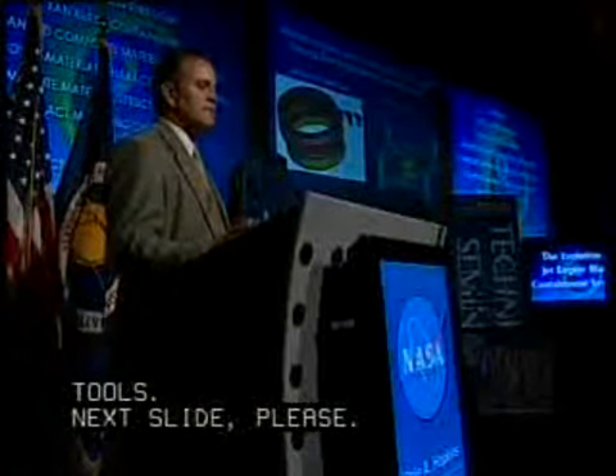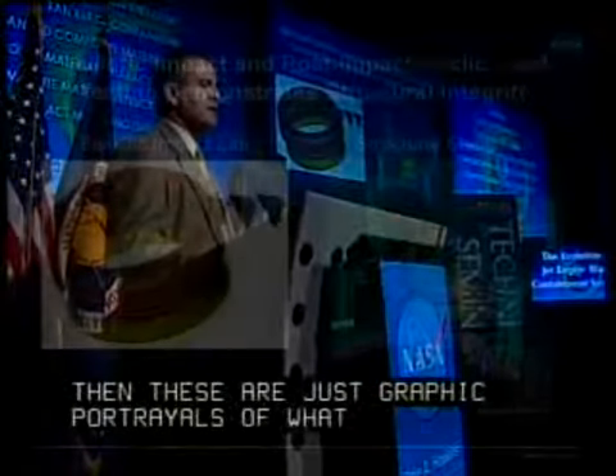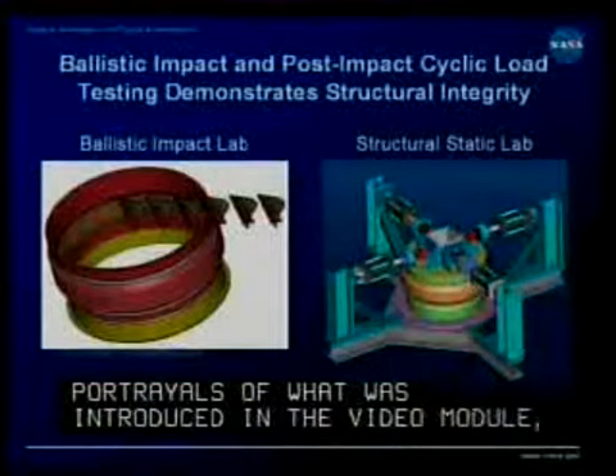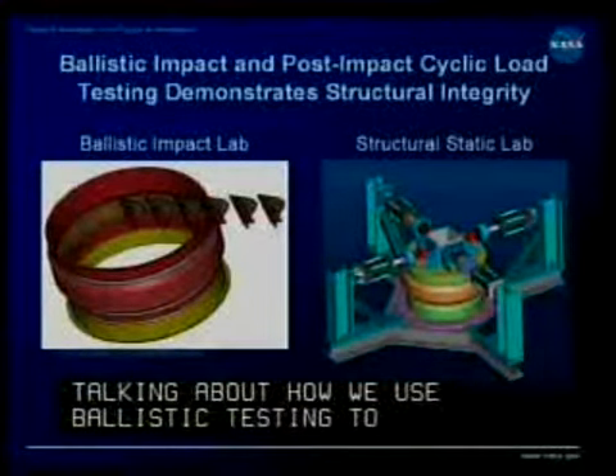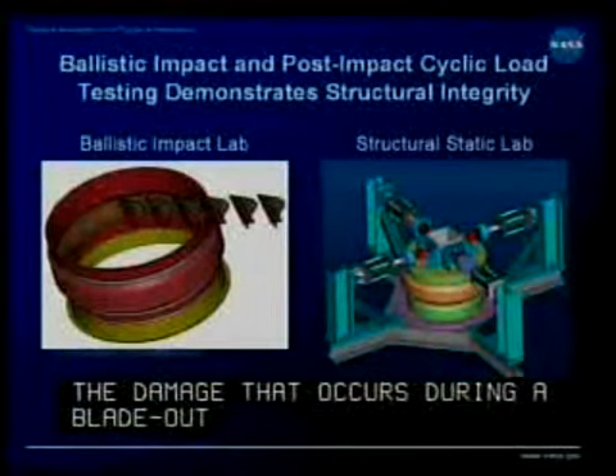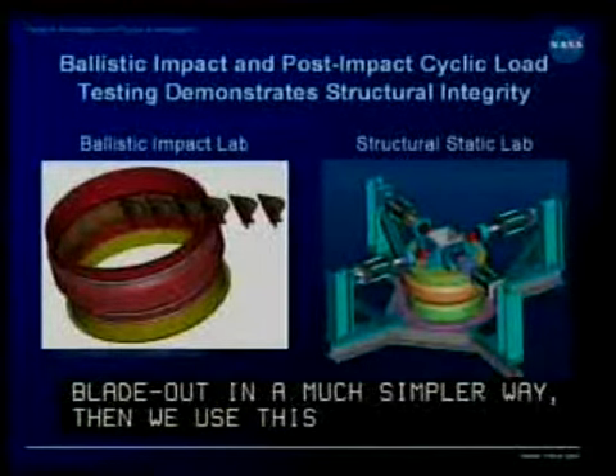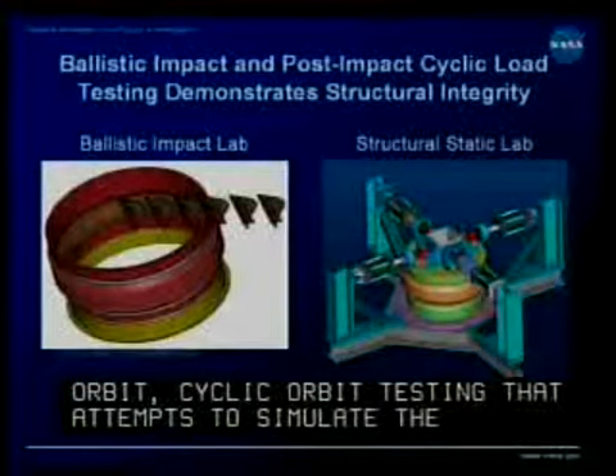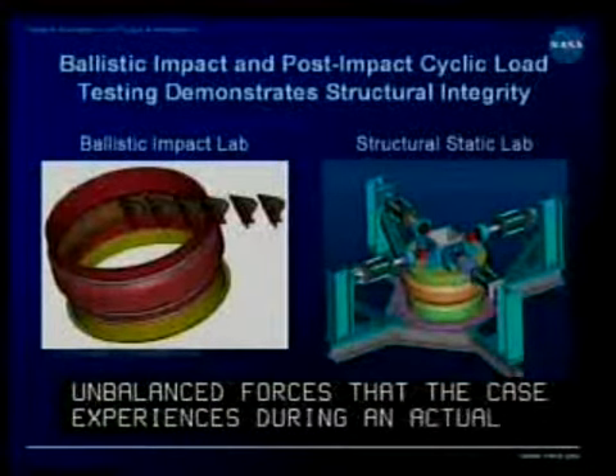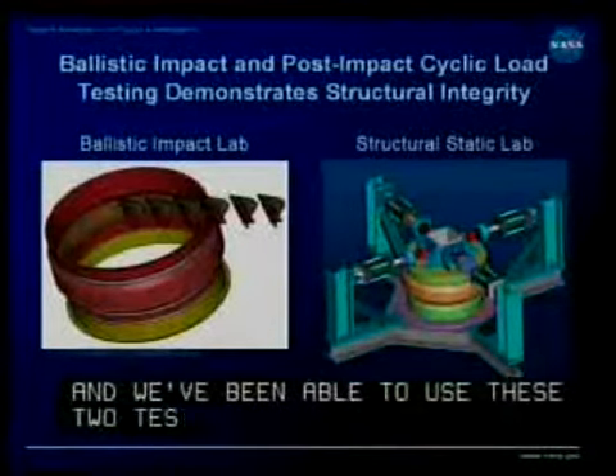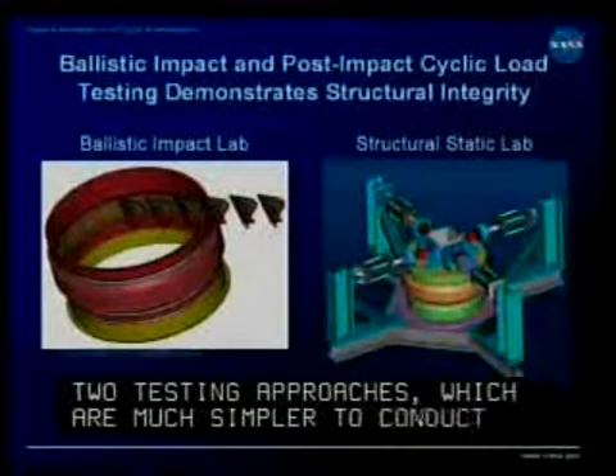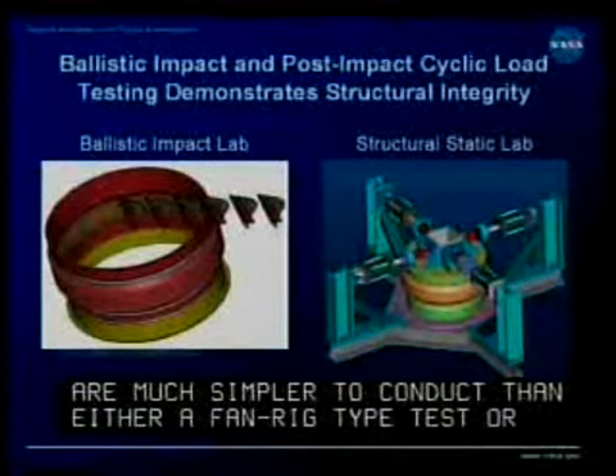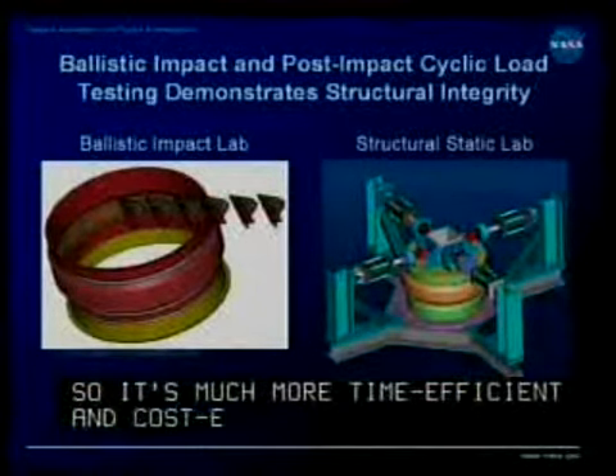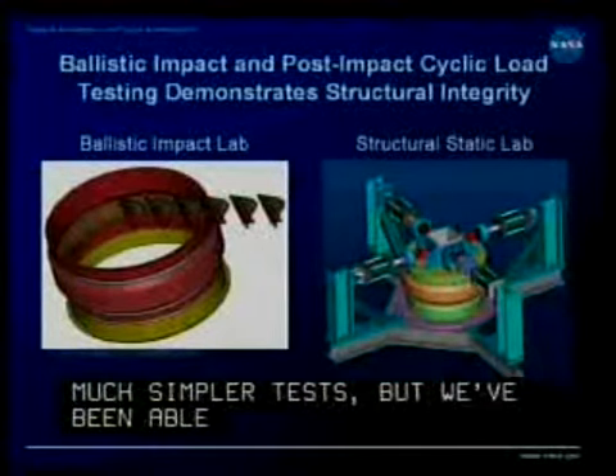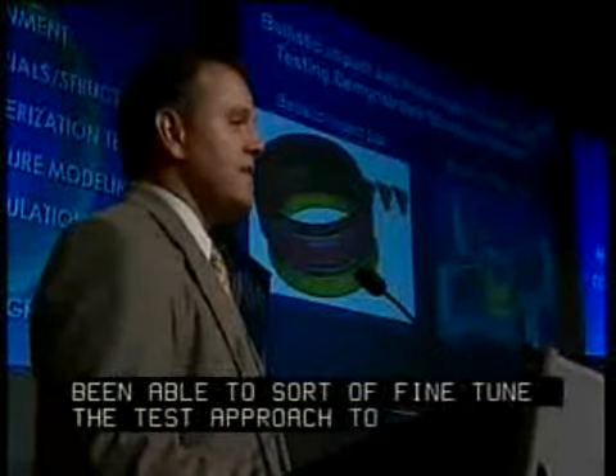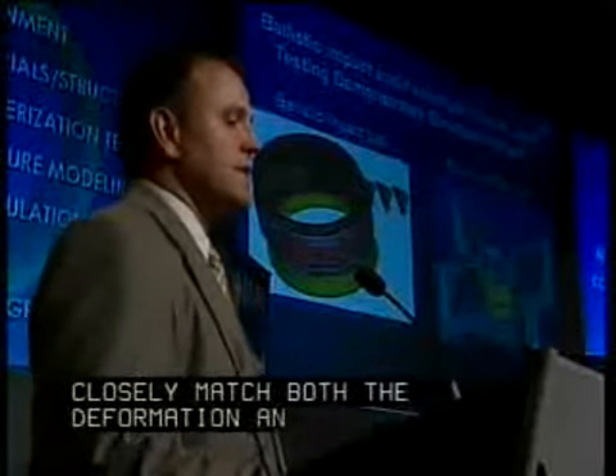Then these are just graphic portrayals of what was introduced in the video module, talking about how we use ballistic testing to simulate the damage that occurs during a blade out in a much simpler way. And then we use this post-impact cyclic orbit testing that attempts to simulate the unbalanced forces that the case experiences during an actual blade out event. And we've been able to use these two testing approaches, which are much simpler to conduct than either a fan rig type test or obviously a full engine test. So it's much more time efficient and cost efficient to do these much simpler tests. But we've been able to fine tune the test approach to very closely match both the deformation and the failure mechanisms that are observed during a real engine blade out test. Next slide.